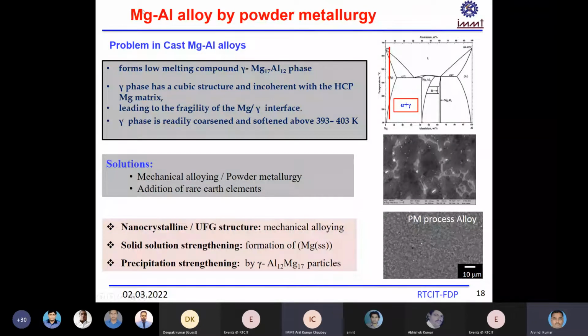So what are the problems in magnesium aluminum alloys? If you look at the phase diagram of magnesium aluminum, the solid solubility of aluminum in magnesium is less than 1% at room temperature. So when you melt, add aluminum to magnesium, and then solidify to room temperature, you come to the two-phase region, with the alpha and gamma phases. Gamma is the magnesium 17 aluminum 12 phase, which is a brittle phase. This phase has a BCC structure, which is incoherent with the magnesium matrix, which has an HCP structure.